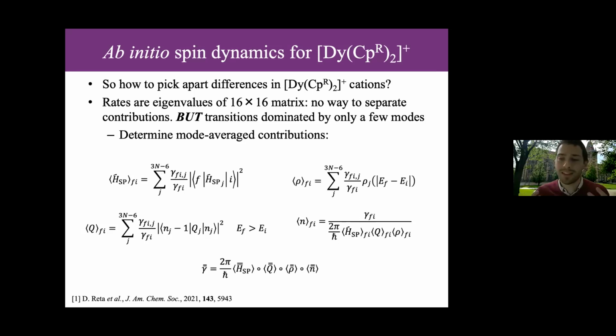So what is the multiplicative factor? Once you've averaged those quantities over all of your modes, what is the effective number of modes you have that are giving you the actual total ab initio relaxation rate for that element? And so once you do that, you have these matrices which define these four components. And so you can reconstruct or decompose, whichever way you want to call it, the total 16 by 16 rate matrix here into these four different matrices.